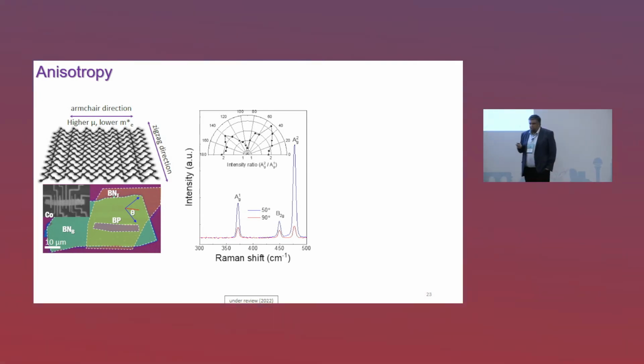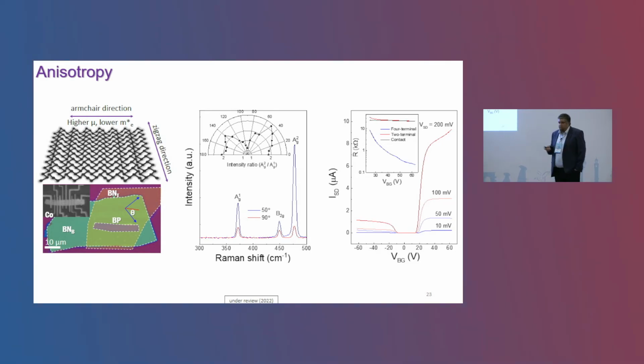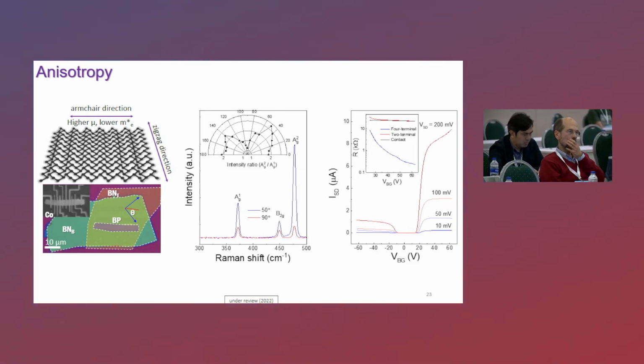But as I mentioned, the material has a highly anisotropic crystal structure, meaning that some edges are terminated with armchair, the others are zigzag edges, and it's also very puckered. So the question is, if the spins are pointing out of plane or in plane, or along the armchair or zigzag edge, does the spin property change? To answer this, we fabricated new devices, using Raman spectroscopy to determine the crystal orientation, and then we put the electrodes accordingly. Even in these devices, we could see quite high mobilities exceeding 4,000 cm² per volt per second.